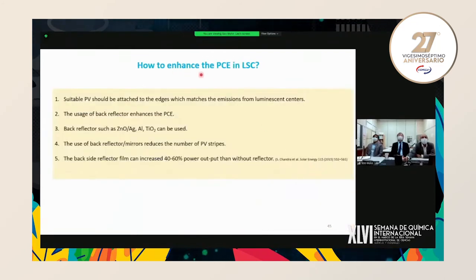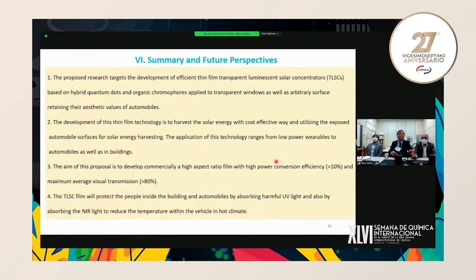So how to enhance the PCE, meaning power conversion efficiency, in LSC? Suitable PV should be attached to the edges, which matches the emission from luminescent centers. The use of back reflector enhances the PCE. Back reflectors such as zinc oxide, silver, aluminum, titanium dioxide can be used. The use of back reflector mirrors reduces the number of PV stripes, and it will be cost effective also. The backside reflector films can increase 40 to 60% power output than without reflectors. And Professor Lee will conclude this lecture.